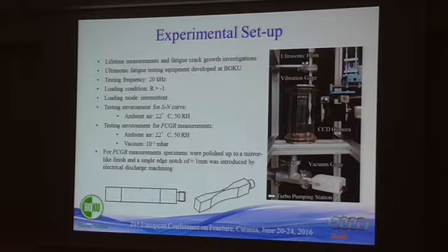Sample preparation for fatigue crack growth rate measurements included a mirror-like finish and the introduction of a single edge notch of approximately 1 millimeter by electrical discharge machining in order to avoid any residual stresses. Fatigue crack growth was observed optically on the specimen surface, as you can see here.